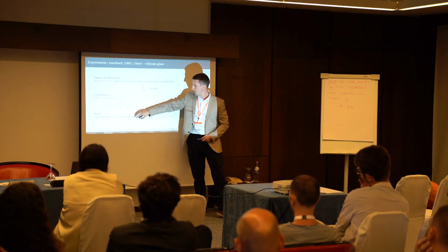If we take the Hertzian theory of contact, and we take the equation for the maximum radial stress, which is at the contact radius at the surface, and we say the material properties are the same, the Poisson ratio is the same, and then we know that this ratio is constant, as it is empirically observed, then in the equation there remains the ball radius.